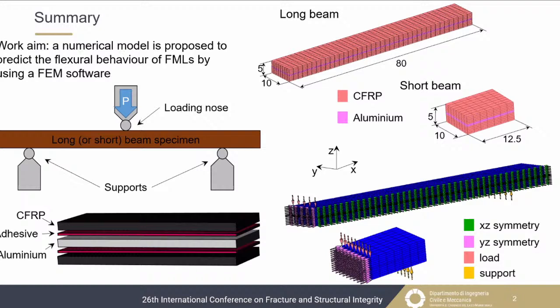This work is based on the simulation of the 3-point bending test. That is a typical test carried out on such kind of material. In particular, we simulated the behavior of both a long and a short beam, because in such a manner we were able to simulate both a normal stress state, so tensile and compressive, and a shear stress state in the case of the short beam.